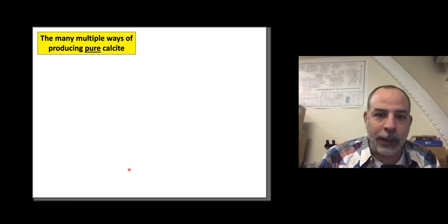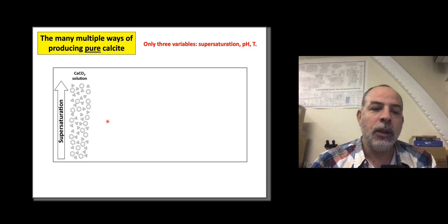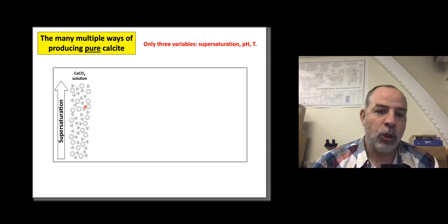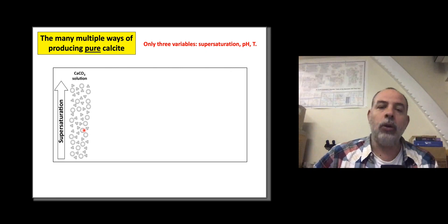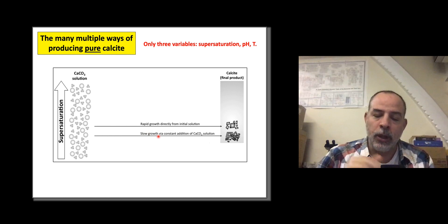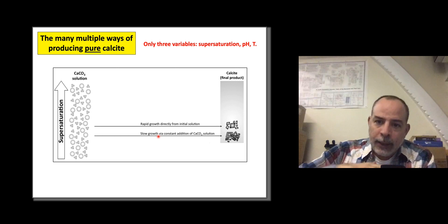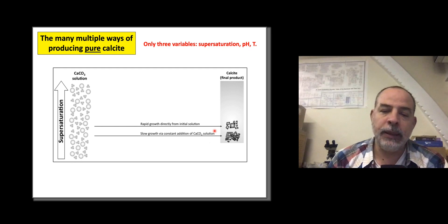You can play at low or high supersaturation — low or high starting concentrations — and the results are going to be completely different. At low supersaturation, if you mix solutions gradually, drop by drop, you achieve slow growth of calcite layer by layer, producing perfect ideal crystals. Mixing instantaneously can give smaller crystals — they are still calcite, but less perfect. This is direct solution-to-calcite crystallization.